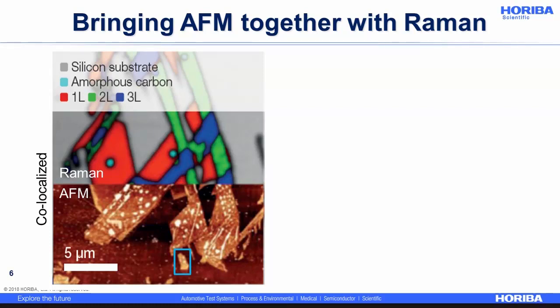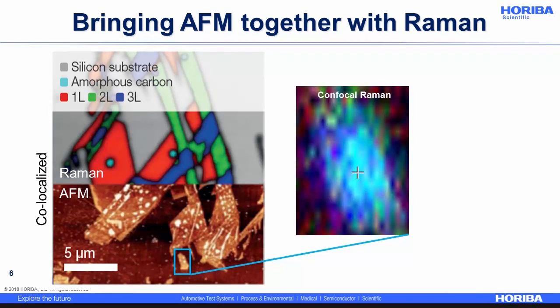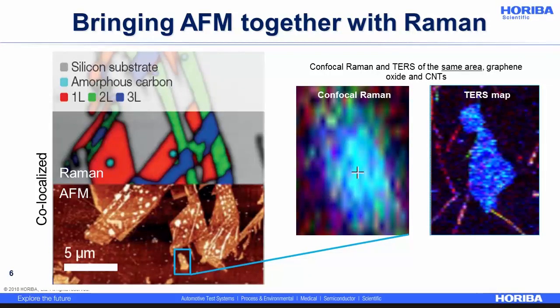Let's zoom on this small piece of flake that you can see in this blue square with a conventional Raman map close to the diffraction limit. It's difficult to see some details in this image. Then we perform a TERS map of the same area with these specific TERS tips, this nano antenna I mentioned. I will describe it a bit later. One can clearly see now the graphene edges thanks to the great improvement of the optical resolution, as well as some carbon nanotubes surrounding the graphene oxide flake. So how is it possible? This is the topic of the first part of this talk.